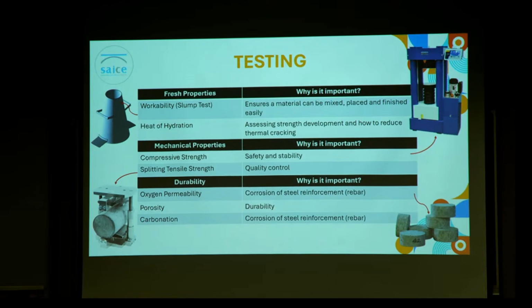All cements were tested under SANS and European standards, allowing cements with low clinker content to be classified as CEM6s, a classification that has not yet been standardized in South Africa. The research evaluated the performance based on fresh properties such as workability and heat of hydration, mechanical properties including compressive and splitting tensile strength, and durability through oxygen permeability index, porosity, and carbonation. All tests were conducted under 2 curing regimes, a 25-degree water bath, and outdoor curing to simulate on-site conditions. The purpose of conducting such a range of experiments was to ensure that the results are evaluated comprehensively. This holistic approach strengthens the findings of the results and also shows its viability for real-world application.